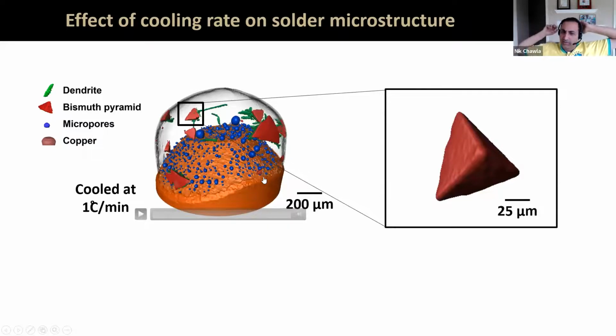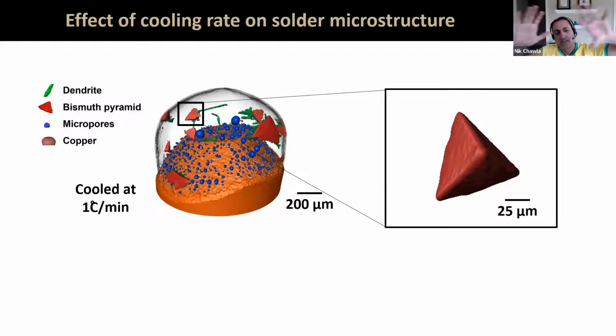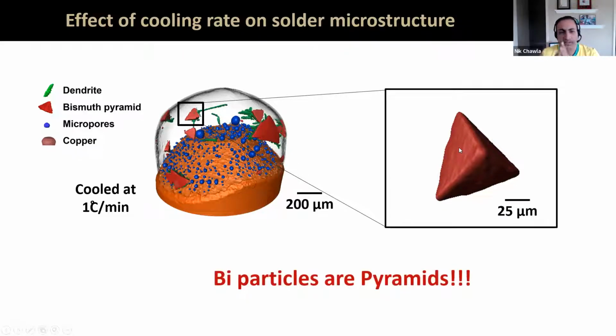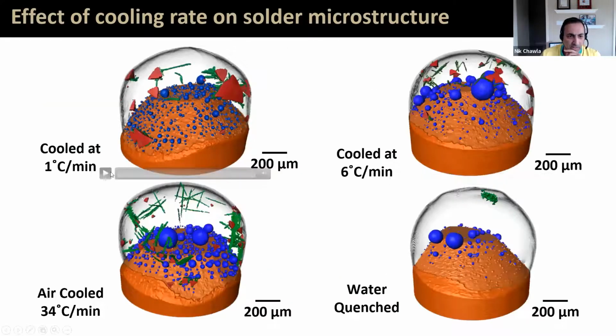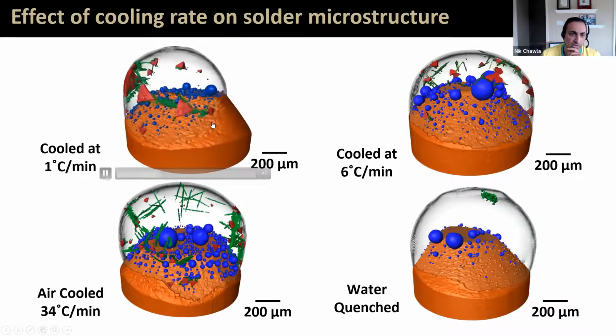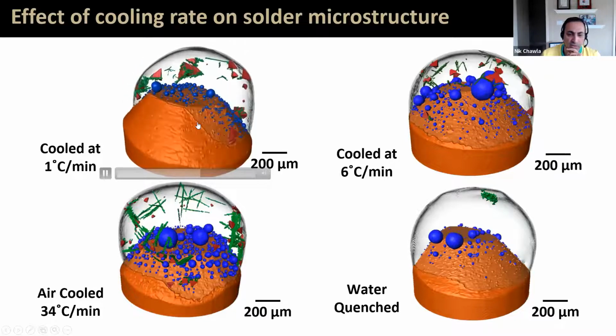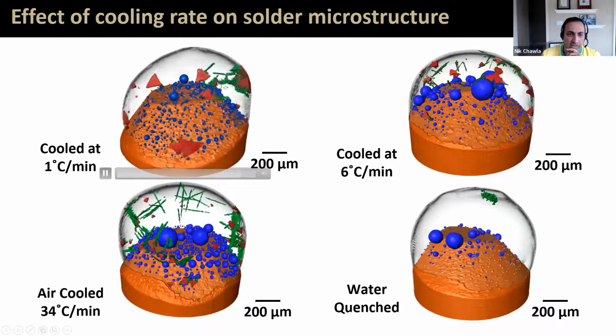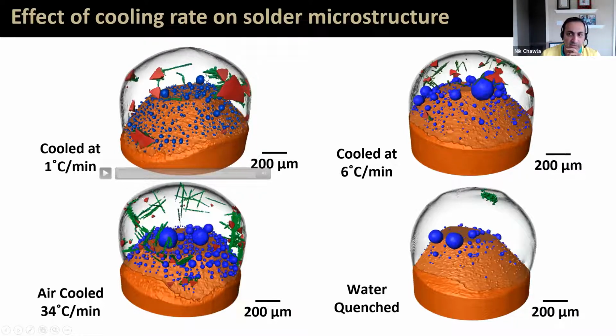So when we were looking at this in the lab, and these are just static after solidification experiments, we noticed that these bismuth particles are tetrahedral in nature. They're almost like perfect pyramids. And the question is, why do they form that way? One thing that you do observe is that as you increase the cooling rate, so here's another animation here. This is at 1 degree C per minute. So this is the slowest cooling rate. You get larger particles, and you also get these tin dendrites that are growing on the sides of these pyramids.